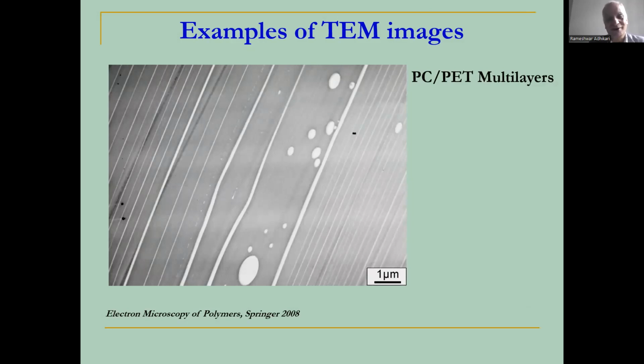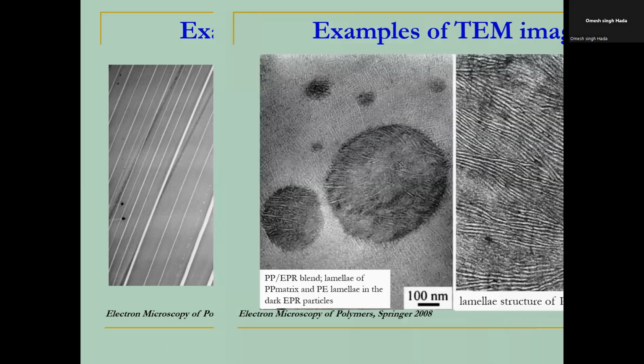So this is another one, multilayers of polycarbonate and polyethylene terephthalate. Here the density of polycarbonate is a little lower than that of polyethylene terephthalate. The staining agent goes, of course, to polycarbonate, as you might have thought. And in this case, the staining agent was ruthenium tetroxide. You can imagine that the darker areas, where there is more ruthenium tetroxide, appear darker, and the brighter areas are, of course, polyethylene terephthalate, PET.